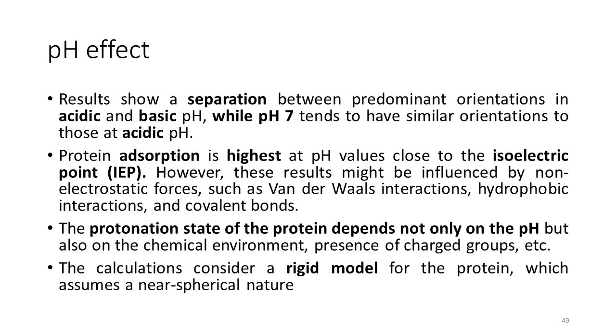In the case of protein adsorption, I can say that it's highest at pH values close to the isoelectric point of the protein. Reading what the bibliography says, the adsorption of the protein doesn't depend only on the pH, obviously. There are other factors like van der Waals, hydrophobic interactions, covalent bonds, etc. However, what I can mention is that the protonation state of the protein at determinate pHs can favor the presence of charged patches. So the effect of the pH is related to the electric potential.